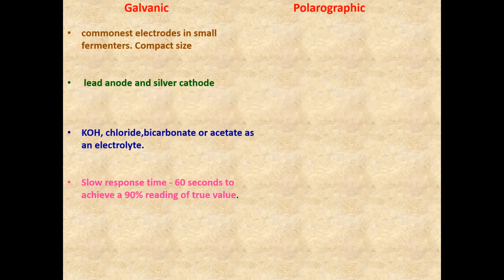So the electrode will not give you the reading immediately. You will get the dissolved oxygen reading in 60 seconds, and that also to achieve only 90% of the true value. So these electrodes are suitable for monitoring very slow changes in the oxygen concentration. Unfortunately, this type of electrode is also very sensitive to temperature fluctuations, which should be compensated for by using a thermistor circuit. So if you are using a galvanic electrode in your fermenter to monitor the dissolved oxygen, you have to use a thermistor circuit as well, because these electrodes are very sensitive to temperature fluctuations and that should be compensated.